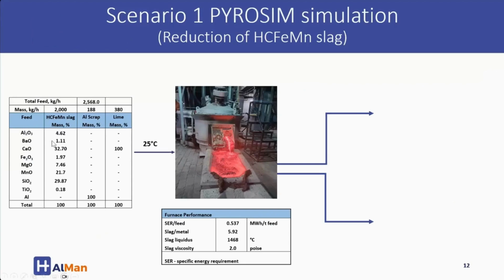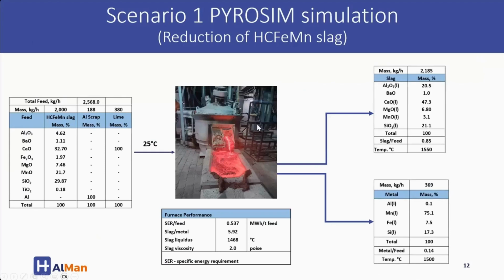As you can see, we have the composition of the high carbon ferromanganese, and the amount of aluminium was based on the recipe mass used to get the highest reduction from crucible scale test work. This high carbon ferromanganese slag has a high concentration of silica and relatively low MnO. We were targeting an alumina content of about 20% in the slag, with about 3% MnO, aiming to get about 75% manganese in the alloy. Also, the estimated specific energy requirement per ton of feed was about 0.5. That's scenario 1, smelting of secondary manganese resource.